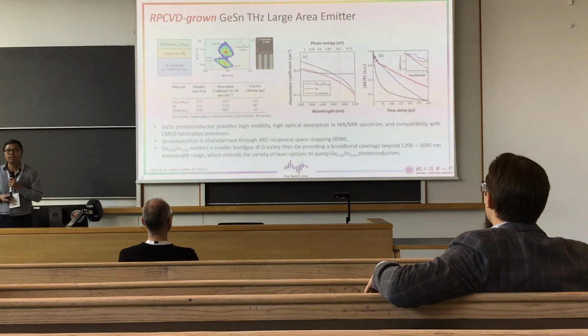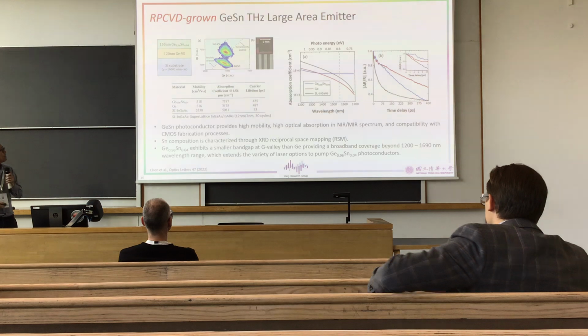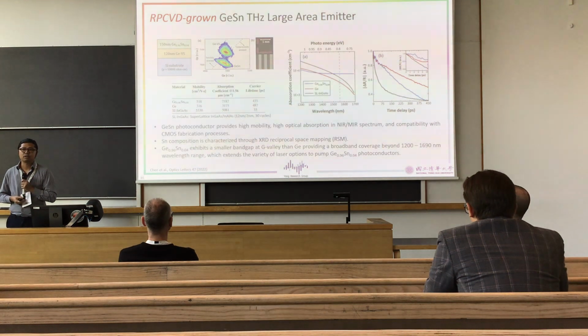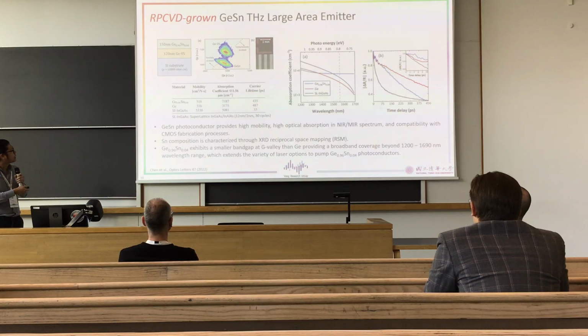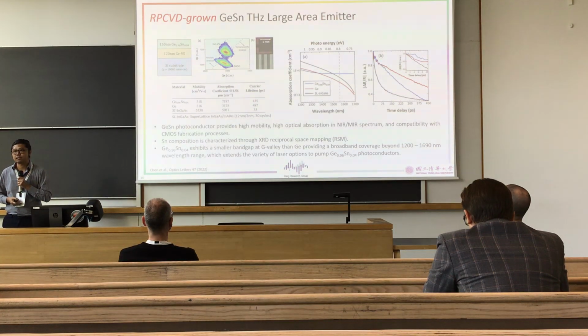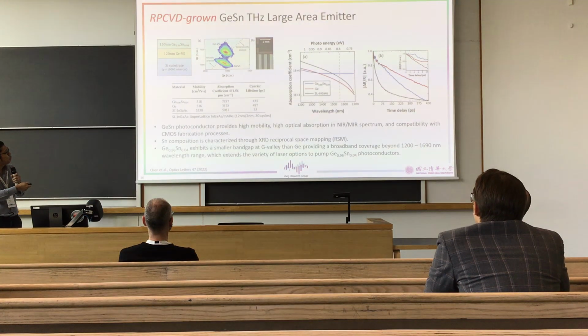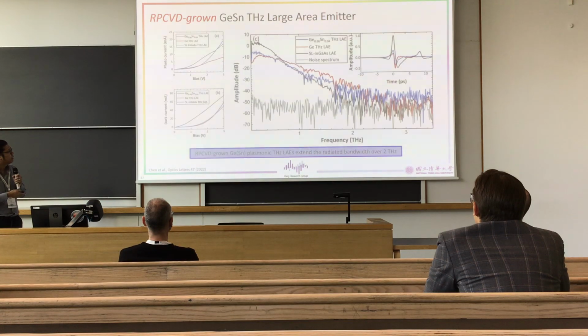Then our second generation germanium terahertz PCA, we go with reduced pressure CVD tools. So we have a very, very high quality germanium thin film. And you can see that this time the carrier lifetime goes to hundreds of picoseconds. You can see here the wavelength, this is the absorption coefficient, and it really expands the wavelength. And now we get more than 100 times higher terahertz radiation. It's almost comparable with the III-V material terahertz PCAs. So we know how to improve it. I mean, the carrier lifetime is so long.